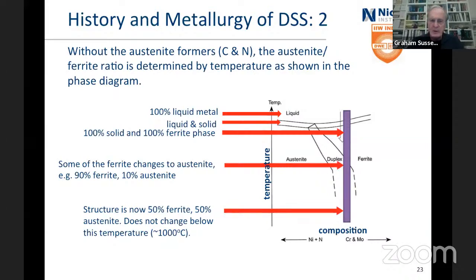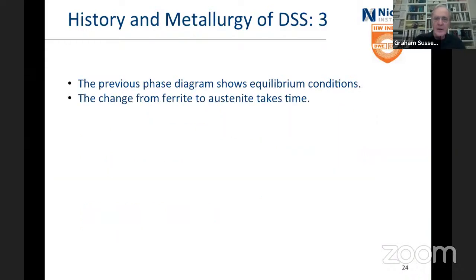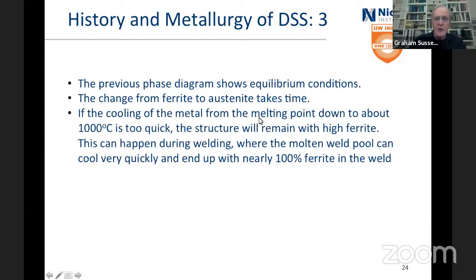Okay, so remember, this is just simply what happens with the austenite formers and the ferrite formers that are metals, not the carbon and the nitrogen. So that's a phase diagram. It's showing equilibrium conditions, and the change from ferrite to austenite takes some time. If the cooling of the metal down to about 1000 is too quick, then there'll be a lot of ferrite. That can happen during welding, of course.